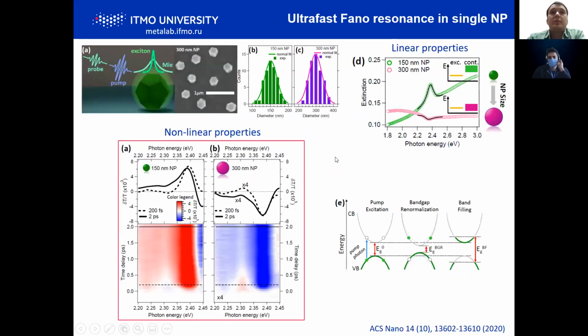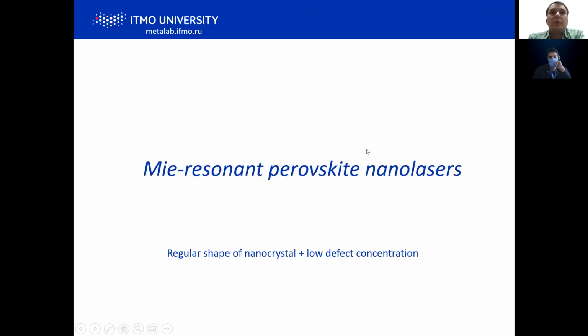And I will just touch on another approach for how we can tune Fano resonance in perovskite nanoparticles. This can also be done by strong pumping of particles. In this work, we checked that particles of different sizes possess different extinction spectra. For small particles, we don't have Fano; we have just a maximum in extinction. But where we have domination of scattering, we have a dip. And in time-resolved photoexcitation experiments, we see for one particle a bleaching effect, and in other particles a decrease of transmittance. So this is, again, due to the specific coupling of exciton with Mie resonance. This is very important for optical applications.